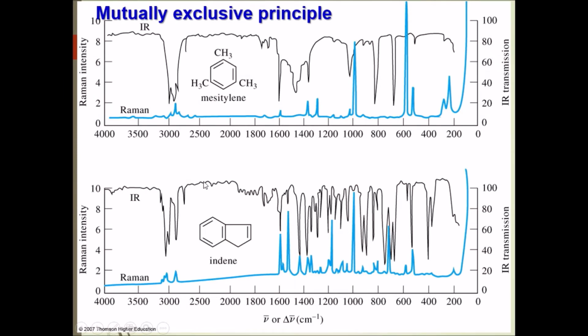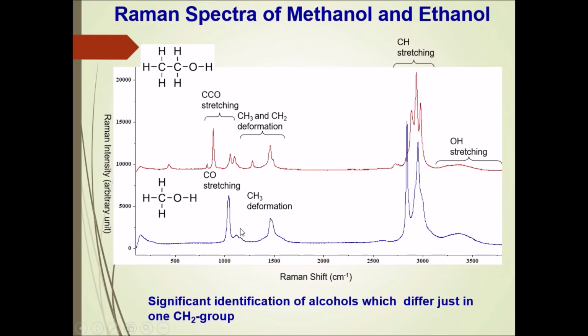Why is Raman spectroscopy a very important technique? Here we can see some practical applications for our microscope. Here we can distinguish between Raman and FTIR. Here we have some organic compounds, like indene. In the FTIR spectrum, we can see a very nice spectrum. It contains many sharp peaks and overlapped peaks and shoulders, so it's somewhat complicated. But the Raman spectrum for the same compound contains few, well-resolved peaks, so we can easily distinguish the composition of our organic compound.